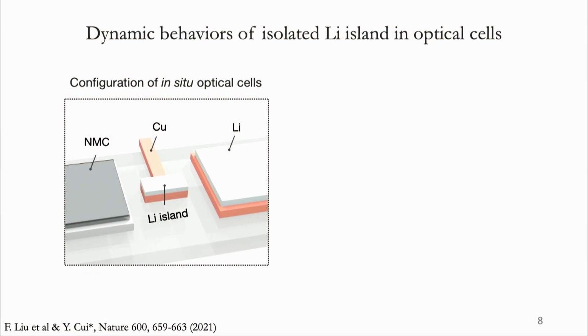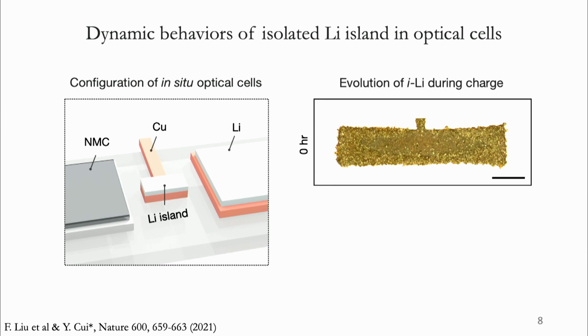So instead of using a two-electrode structure, we designed our own device with a third electrode in between them. We patterned a copper strip as the island between two electrodes, lithium and NMC cathode, and then we electrochemically deposited lithium metal on it to serve as a lithium island. So this is what we observe. Before we cycle the battery, lithium is homogeneously distributed on this island.